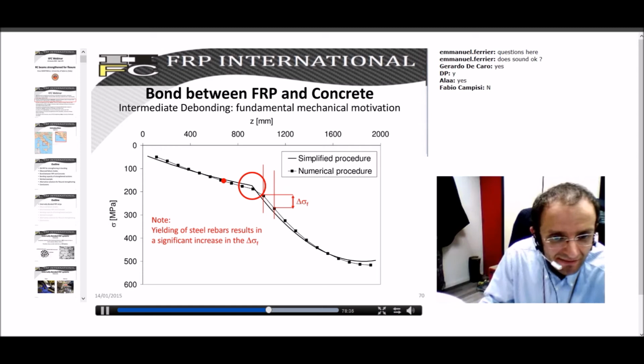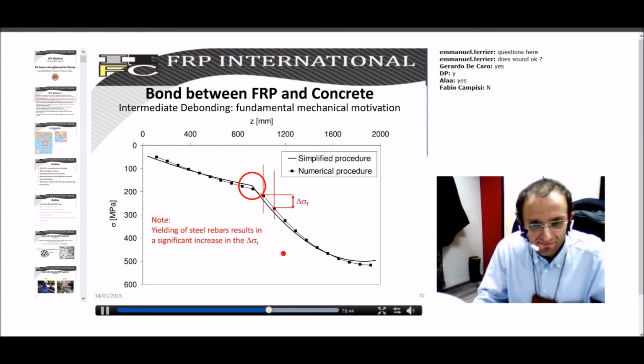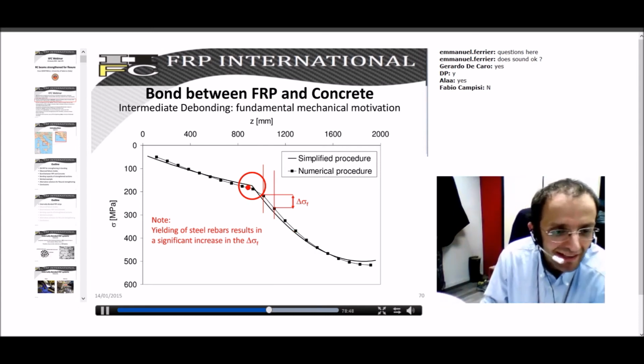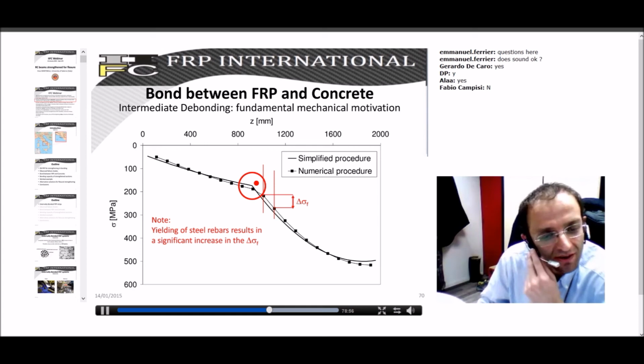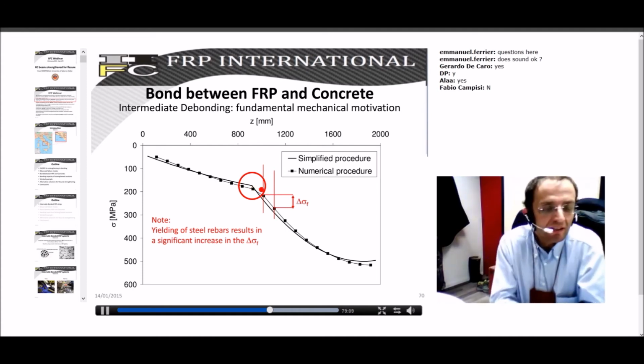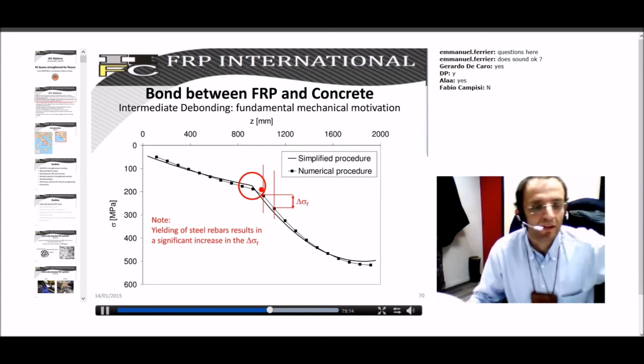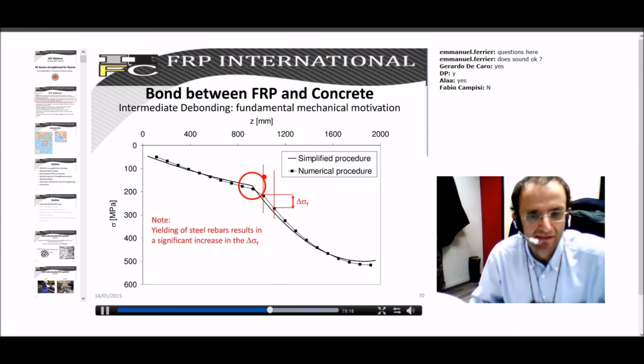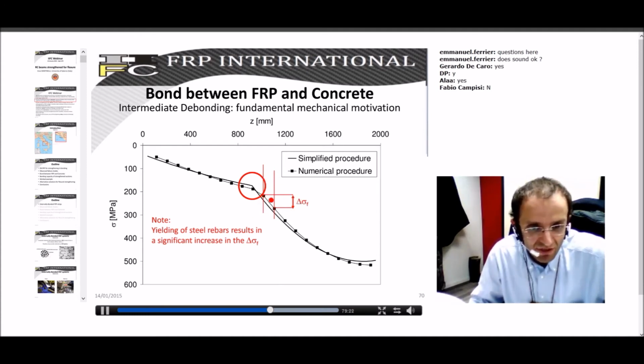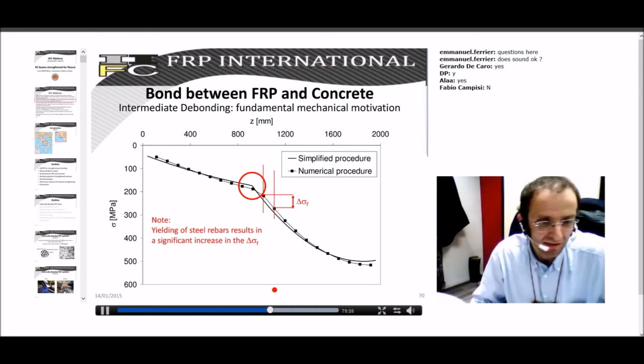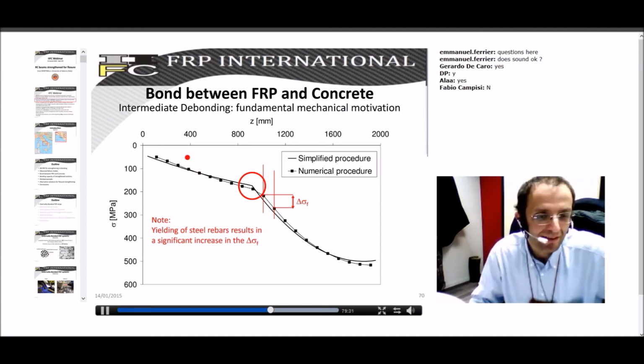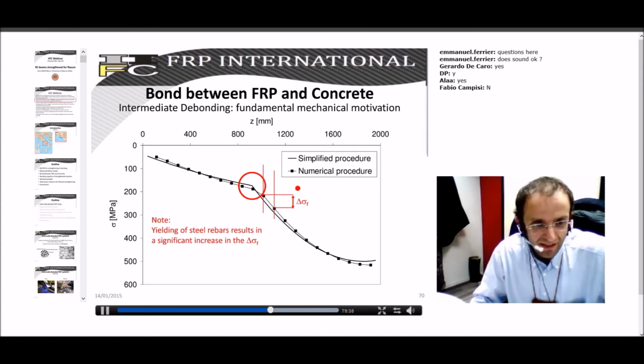As you see here, delta sigma in terms of stresses is really increased after yielding. So, as you see from this graph, delta sigma in the external strengthening is really boosted, is really stronger, or as you can see, more rapid after the occurrence of yielding of the internal bar, because after yielding, the only external reinforcement is the FRP strip. So for any increase on the moment, you have an increase in the fiber. So here, for instance, you see that the delta sigma is much bigger in the yielded part than in the non-yielded part, even though theoretically the moment gradient would be bigger here than here. So this is the delta sigma in terms of stresses.